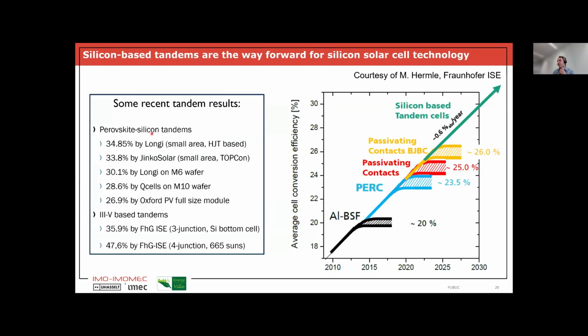And just to show you some recent tandem results, the world record solar cell for perovskite on silicon was also recently broken, is now at 34.8%, also by the same company, Longi, that has the world record for the single junction. So for a single junction, we have reached 27.8%. And if we put a perovskite on top, we actually increase by 7% absolute to 34. So it's really worthwhile to go to these tandems.